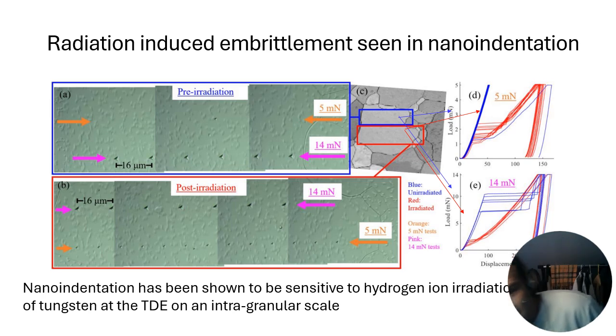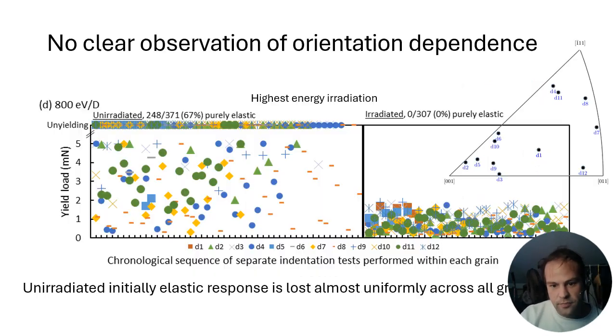So one thing I've seen with nano indentation is that we can do testing on a grain by grain basis, before and after irradiation, to characterize near threshold displacement energy effects. Now, we haven't seen a clear dependence on orientation. So I'll show you these various different specimens. The first specimen we tried at a sufficiently high energy that, from previous experience in the lab, we had reason to expect that we are creating displacement damage, that we are imparting energy above the TDE.